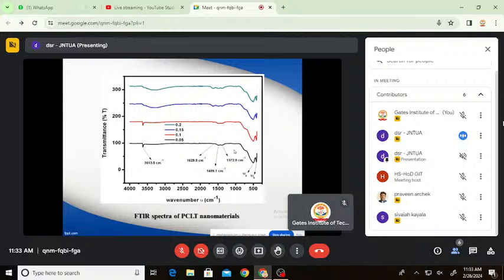Increasing the y value from 0.05 to 0.2 causes the shifting of nu A towards lower values, from 512 to 417 per centimeter. This may be due to favorable occupation of cobalt, lanthanum, and lead ions at the A site. Besides that, at the B site, the occupancy of Ti ions justifies the constant wave number of 408 per centimeter.